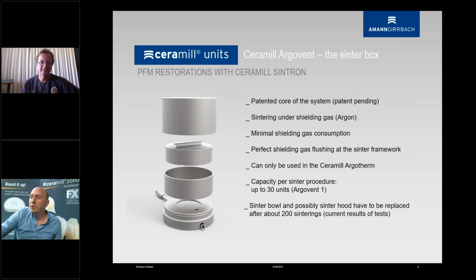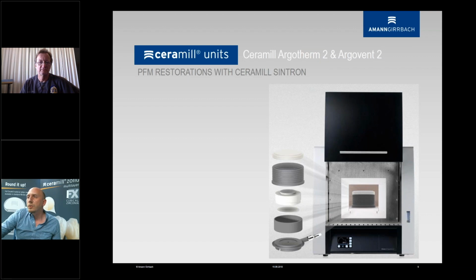So here you see the first generation Argon box. We were able to hold approximately 30 units in it. And the sinter bowl and possibly the sinter hood needed replacement after about 200 sinter cycles, more or less, depending on how well you took care of it. And now we have the Argon box 2, where you see immediately the size has changed, and all of those are no longer considered wear items. The first generation was a cast metal. This is a very different material here, and the way it's made, and the tolerances have increased as well.